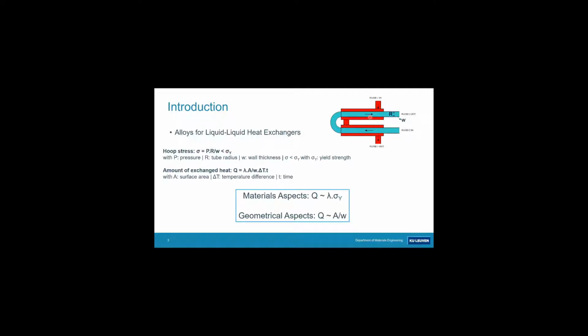So that basically means the thinner you can make the separation wall, the more heat you can exchange. But of course, the separation wall has to be strong enough to withstand the pressure acting on it. And there are hoop stresses acting on it. And they should not exceed a yield stress, because otherwise your plate will plastically deform, which you don't want in this case. So if you want to maximize this Q, so the amount of exchanged heat, you see, you can work on the material. And of course, you can also work on the design. And that makes the combination of highly conductive and strong alloys with geometrical design freedom, and then we immediately talk about additive manufacturing technologies, very interesting.